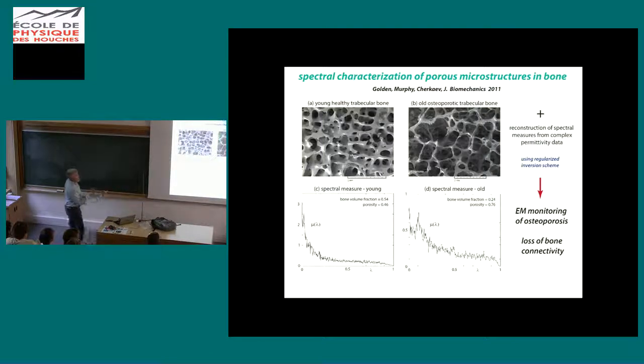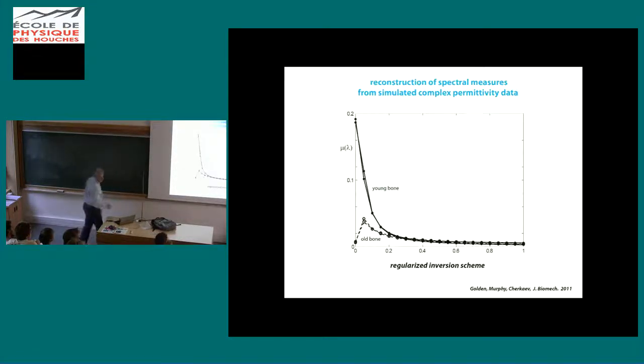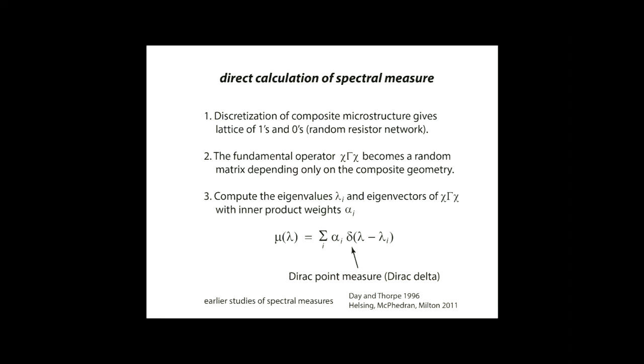Here's good healthy bone, here's more older osteoporotic bone, here's the spectral measures directly calculated here. You see that this goes up to 3, that only goes up to 1, so the mass of this is much less in the older osteoporotic bone. And then this is the inversion scheme, actually taking complex permittivity data and then reconstructing the spectral measure showing the difference between the young healthy bone and the older osteoporotic bone.